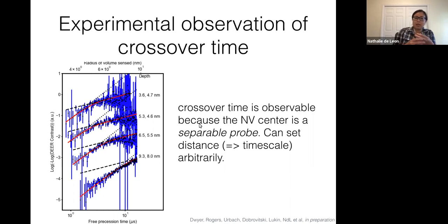But the key thing here is that the reason that the crossover time is observable is because the NV center is a geometrically separable probe. So we can just set the distance from this bath arbitrarily rather than interrogating the bath directly. And if you interrogated the bath directly, this time would be set by the configuration with the closest separation between spins, which could be at lattice constant spacing. So normally this would be at inaccessibly short timescales, but here, because we can move the NV center arbitrarily far away from this bath, we can now push this into experimentally accessible timescales.